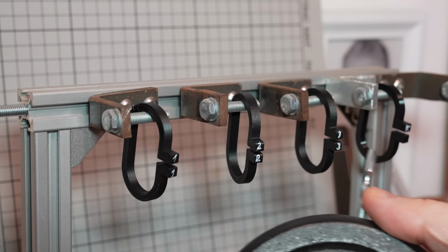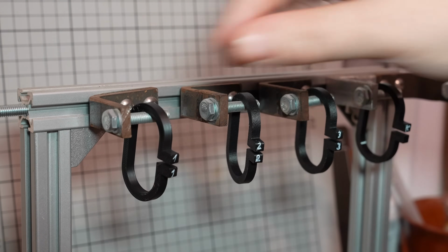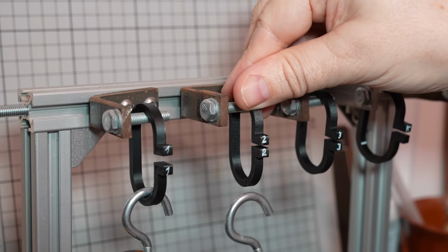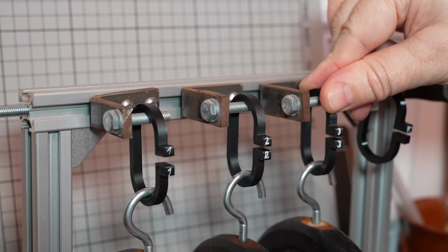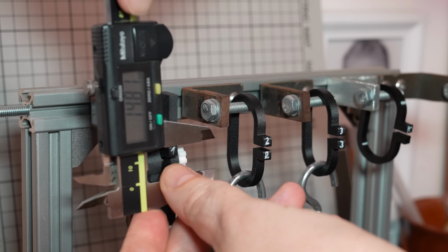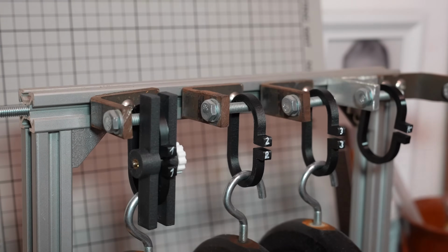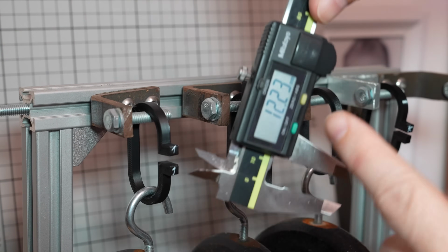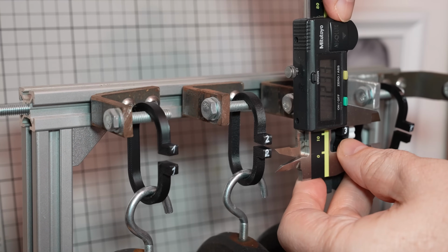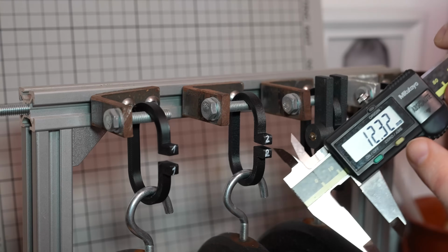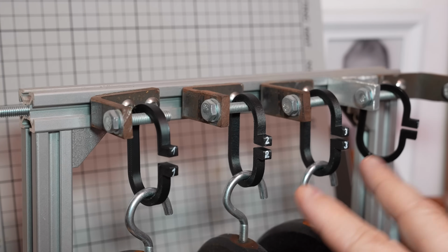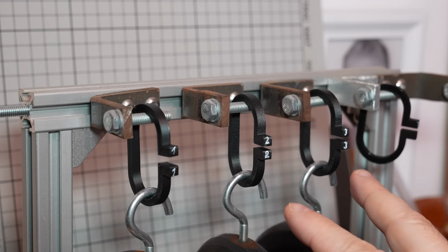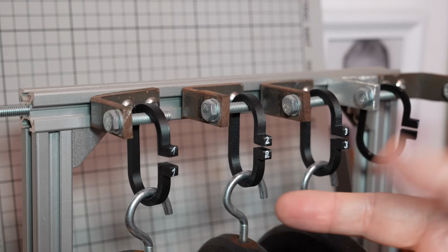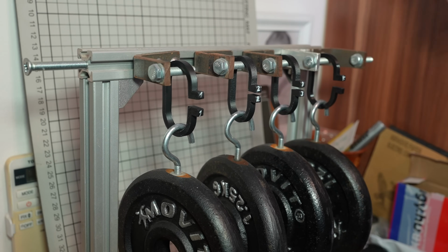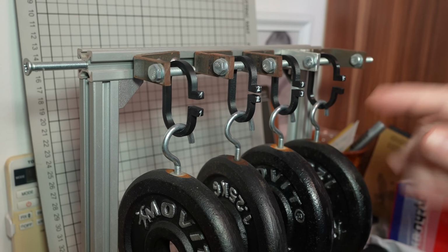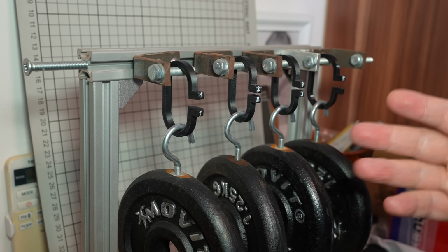Creep test, the deformation under the constant load of 1.25 kilograms. 14.81, 12.23, 12.32. From these three, two carbon fiber versions are really good in these very stiff materials and they deform very minimally compared to PPA. This is the last fifth day and only on the PPA I can see some deformation. On the other two carbon fiber version, basically this creeping is near zero.